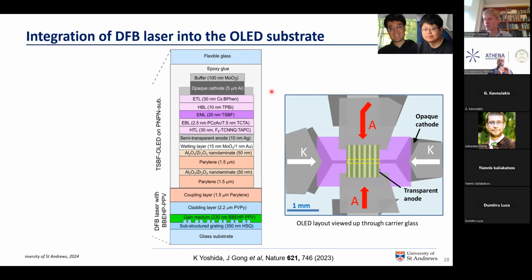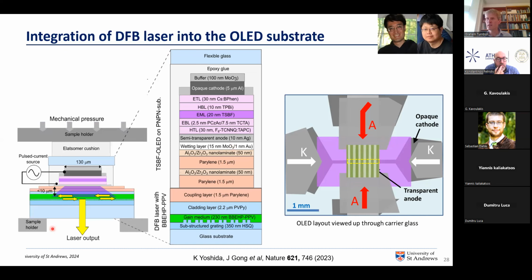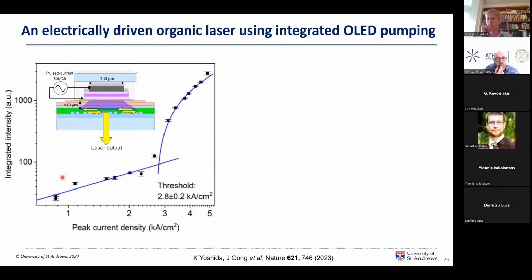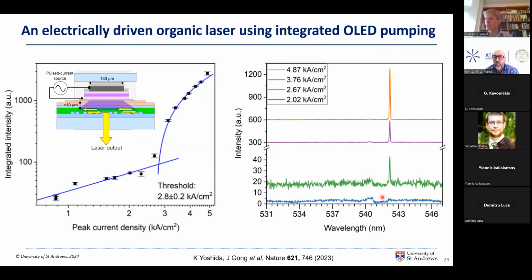So we integrate our organic DFB laser into the substrate of our OLED, and then we electrically drive it with very short current pulses into the OLED. And when we do this, we can drive the laser above threshold. This is a log-log plot, and it shows the electroluminescence, the spontaneous emission from the device at low current densities, and then above about 3 kiloamps per square centimeter, we can drive the laser above threshold. The laser emits a single frequency emission that we can identify as being on a photonic stop band edge of the distributed feedback structure.